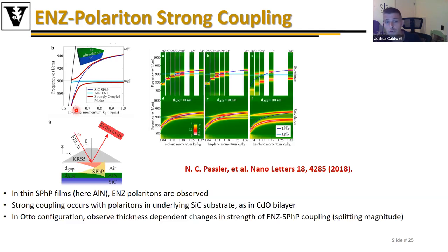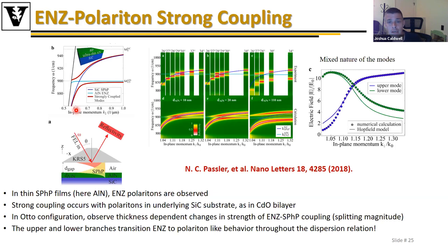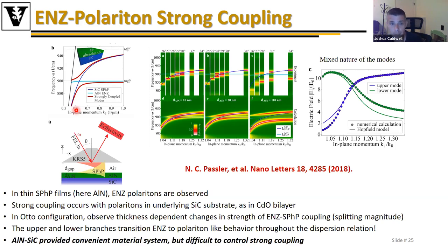And again, the control of the oscillator strength by changing the thickness of that top layer controls the strength of that strong coupling. And again, I'll just point out one of the key benefits of these strongly coupled systems is that you result in multiple branches of these modes, which then take on hybridized properties of the two constituent layers.